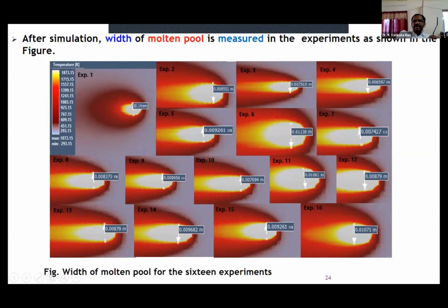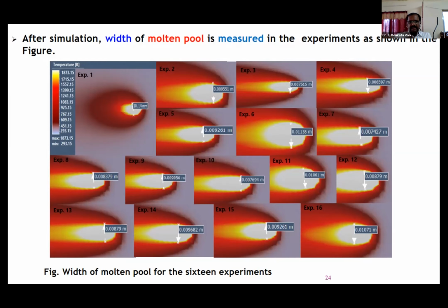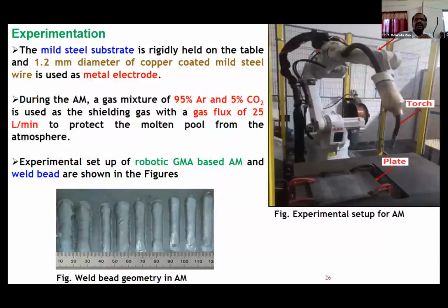To confirm this, for the experiments conducted by other researchers using the high-speed video camera, at those working conditions we performed this simulation and compared it. After confirming the accuracy of this software, only then did we use the software here to predict the width of weld pool. Okay, we found the width of weld pool.